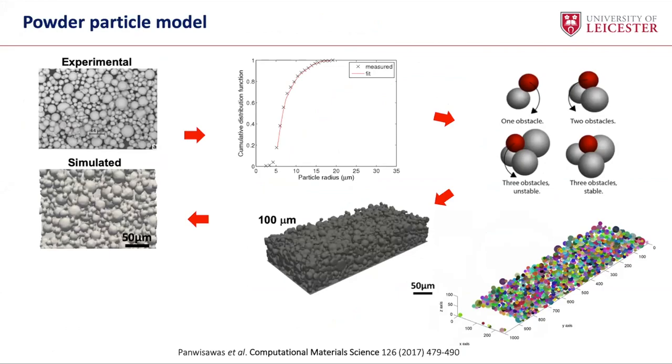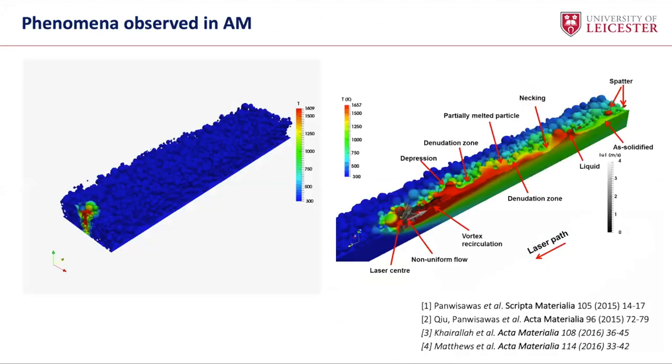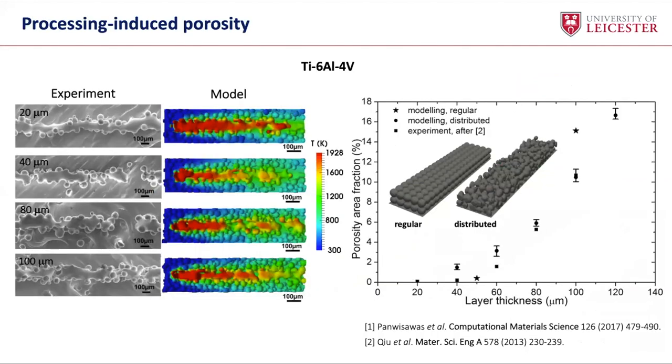I start from powder particle measurement using laser, and then I fit the powder particles, arrange them in the bed, and simulate the spreading of the powder in the powder-based process. After that, I apply the laser beam, making sure that I capture all the physical phenomena happening during the process. Hence we can use this model to predict something like the porosity level.